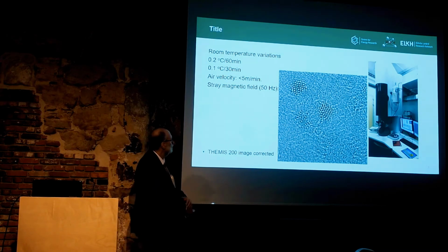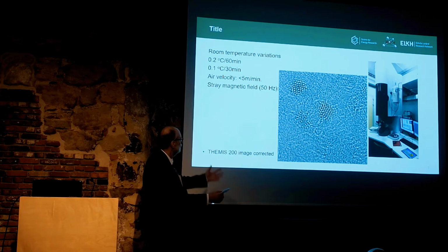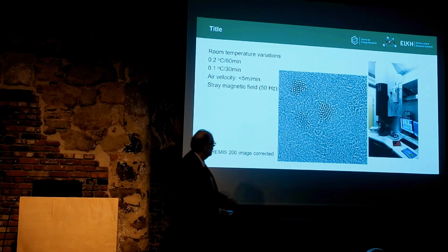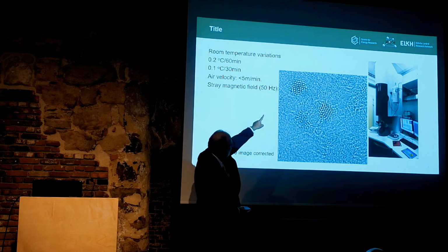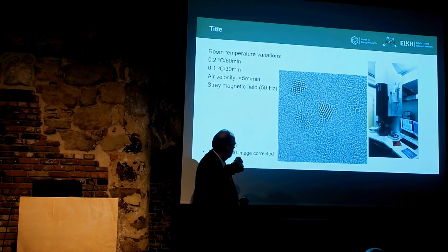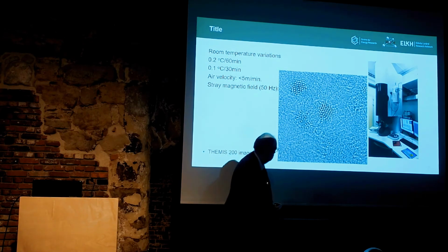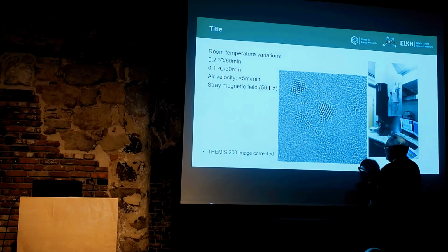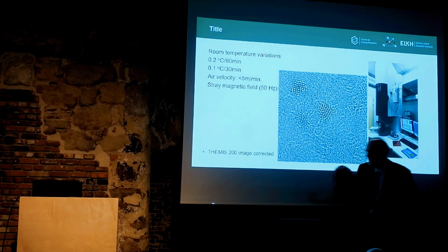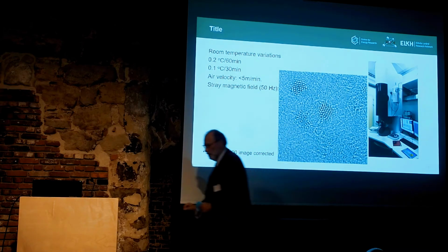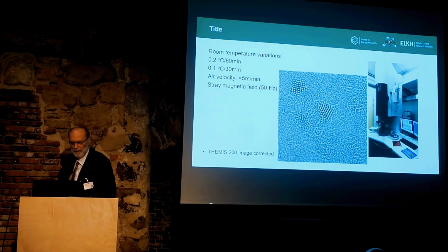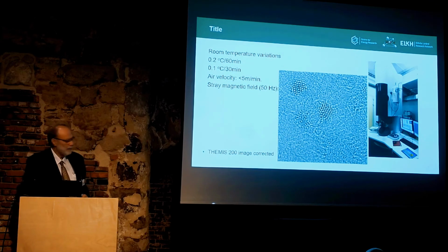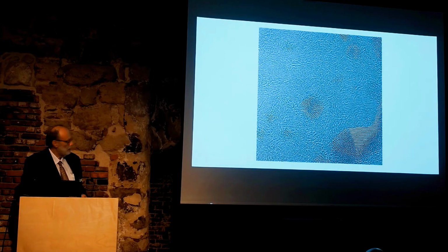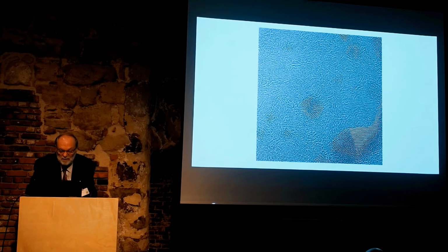Okay, atomic images of small crystals are not so surprising, but on this image we don't care about the ones which are big. We take care of this and this, because these are small platinum crystals, but those ones are single platinum atoms which we can identify on the surface of carbon. And I hope that this will work.